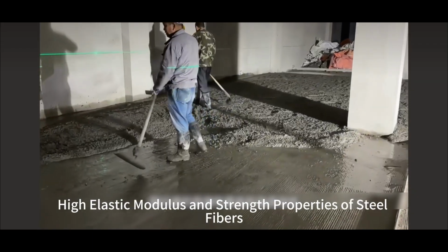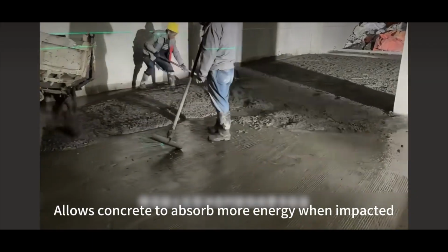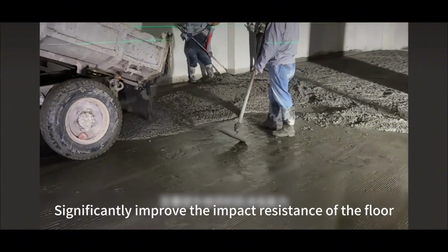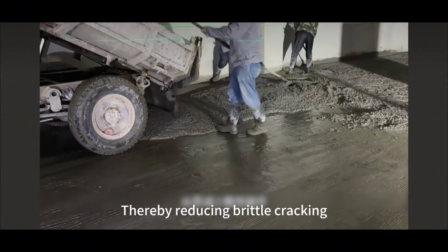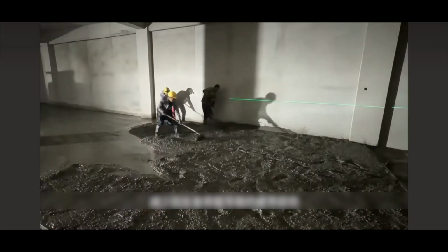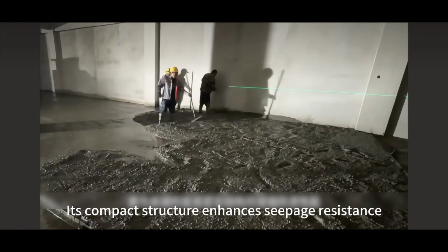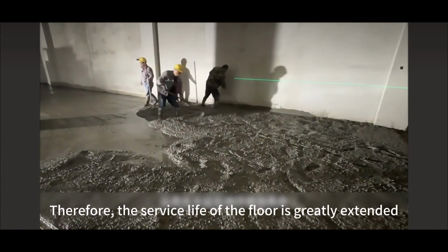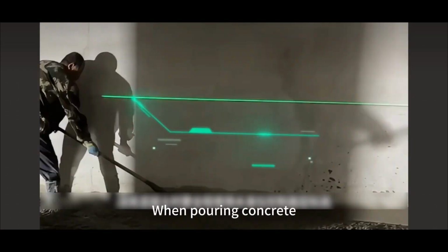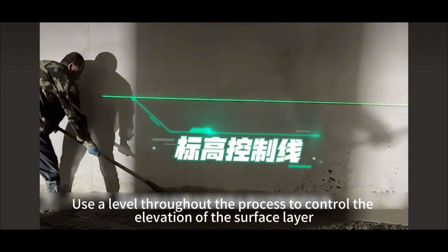High elastic modulus and strength properties of steel fibers allow concrete to absorb more energy when impacted. Significantly improve the impact resistance of the floor, thereby reducing brittle cracking. Steel fiber concrete can delay crack propagation. Reduce fatigue damage caused by repeated impact. And here's the thing, its compact structure enhances seepage resistance. Therefore, the service life of the floor is greatly extended. When pouring concrete, use a level throughout the process to control the elevation of the surface layer.